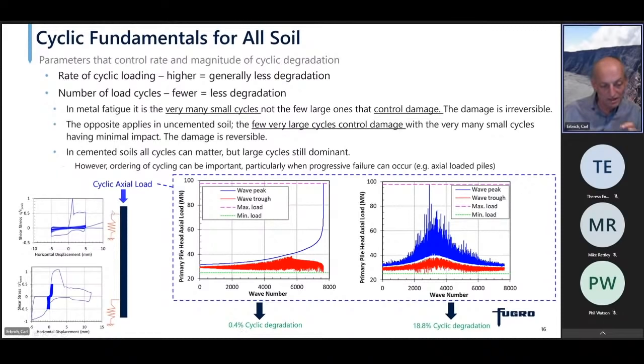The big cycles break the cementation, but once we've broken the cementation, the small cycles can work that element of soil and wear it down basically until it's got very low residual. And then you hit it subsequently with another big cycle in a random order, and you then have propagated the damage further down, and you now break another bit of soil. So gradually you propagate the damage further and further down the pile. So that's really very important when we've got brittle materials: the ordering becomes important.